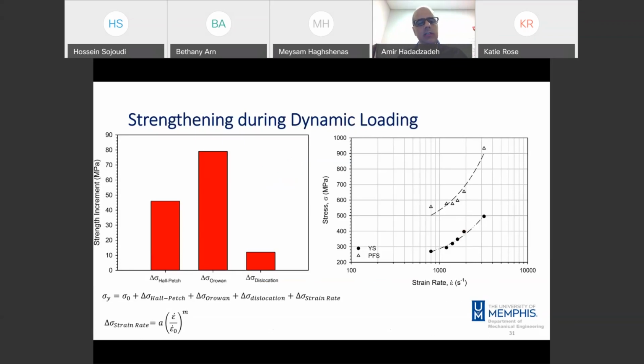Again, to study that, I used the same hardening fundamentals: Hall-Petch, Orowan, and dislocation. And now we have another component, which is the strength increment due to strain rate. And there is a semi-empirical equation for that in literature to correlate the increase in the strength of the material because of strain rate to the level of strain rate, where A and M are material constants. On the right hand side, I have shown the effect of strain rate on the strength of the material, both yield strength and the peak flow stress for different strain rates.